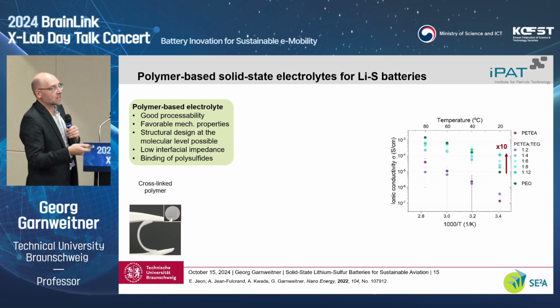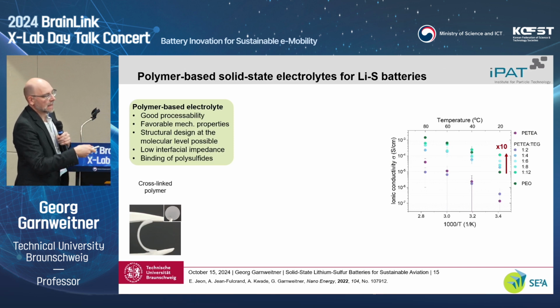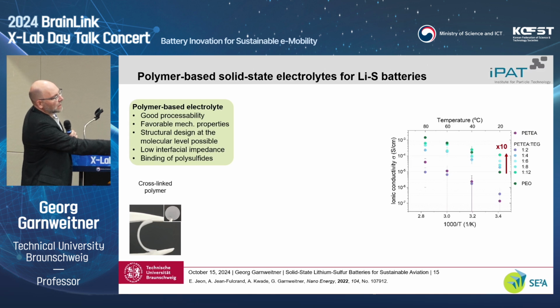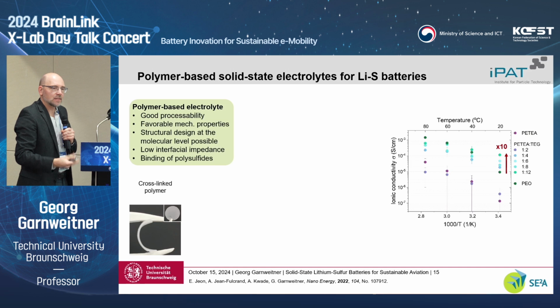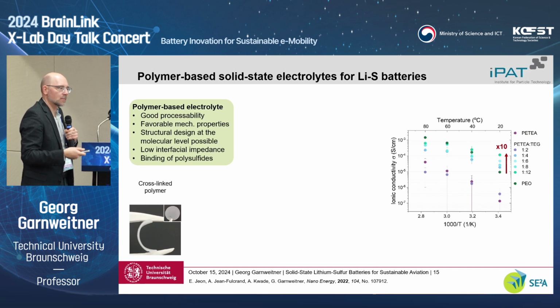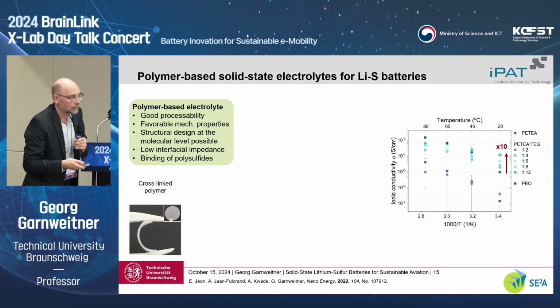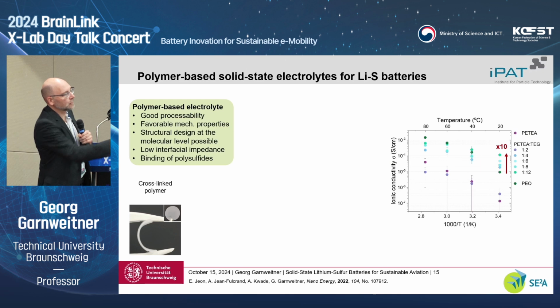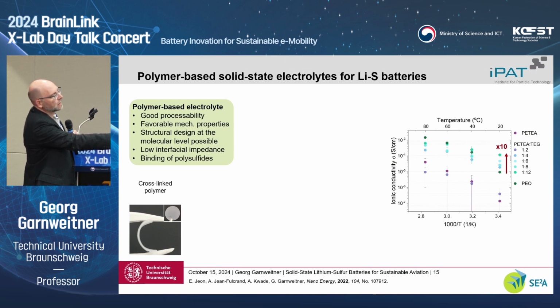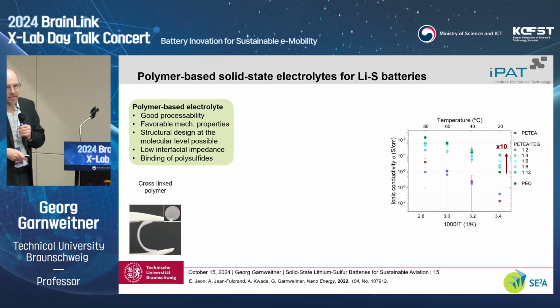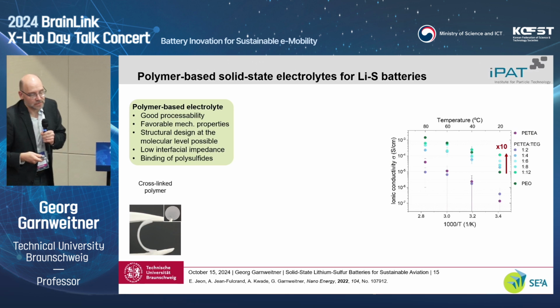Well, we combine it with a second compound, PETEA, where the pure compound has a very low ionic conductivity. But as we combine these two compounds, we get a system that has a much more stable ionic conductivity also over the different temperatures. And you see that with a system of 1 to 12 mixing between the PETEA and triethylene glycol components, we have a 10-fold increase in the ionic conductivity. But that would not be sufficient.